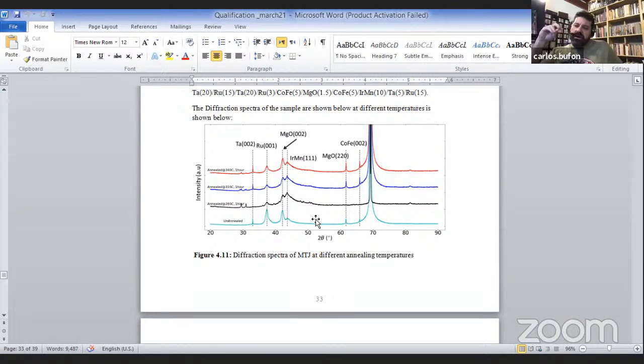My main question is that for a TMR junction, for instance, if you want a good tunneling barrier, you should avoid grain boundaries, because there you have oxygen vacancies and you have transport across these junctions. This might affect your junction, dissipating heat and things like that. My point is, how can you ensure that you don't have such grain boundaries? How can you access this information?